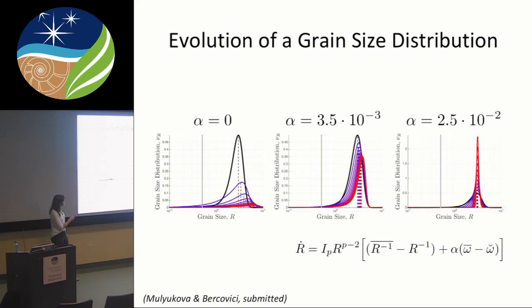If alpha is slightly larger, it's still shifting to the right, but not quite as fast, and it's not really broadening as much anymore. And here, where you reach your alpha where dislocation density is important, instead of shifting to the right and broadening, you're actually collapsing your entire grain size distribution. So all your grain sizes are shrinking down to your now existing steady state grain size. Okay, so this is where all the grains will want to be, that 1 grain size.